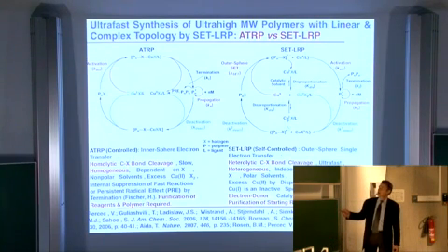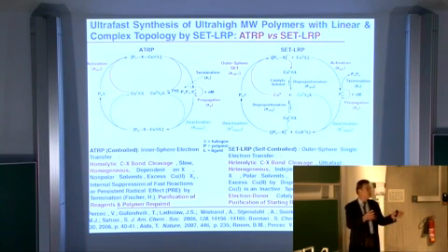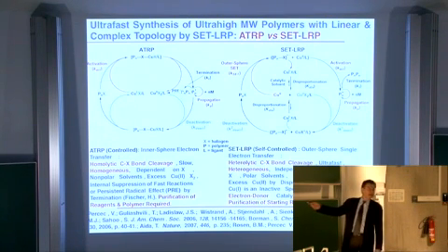The following. A low oxidation state metal that is usually copper-1 takes an alkyl halide and, via a process that the authors claimed to involve a homolytic bond cleavage followed by one electron transfer, provides a radical.